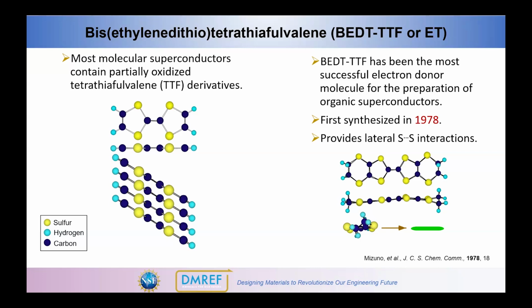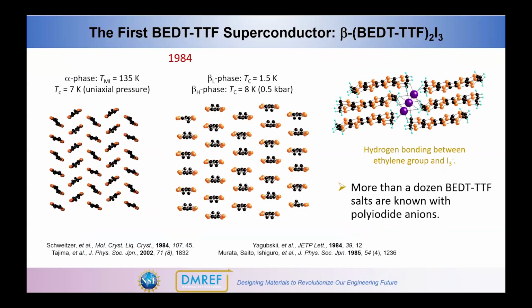And so most organic superconductors, probably, maybe a correct statement, have extended this basic TTF framework to the BEDT-TTF molecule. It puts this extra six-member ring on the ends of the TTF molecule. And this provides, because of the extent of these sulfur atoms going further from the central core of the molecule, more lateral sulfur-sulfur interactions that result in more 2D materials, and probably contributes to the higher superconducting temperatures and more superconductors being formed.